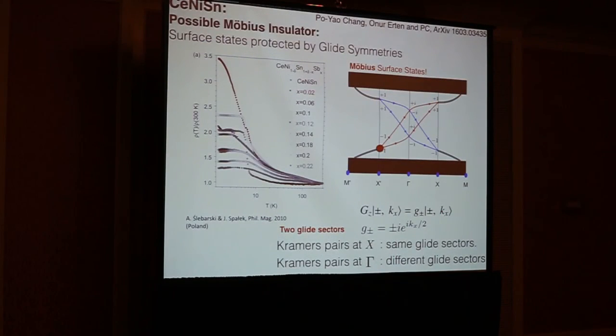And let me just mention a few other things. One of the other systems that may be topological in the heavy fermion systems is cerium nickel tin. This system is a non-symmorphic insulator. It's a semi-metal, and one of the results of this extensive analysis of topological states of matter is that non-symmorphic crystals have glide symmetries that can protect surface states. And they lead to these rather exotic surface states with a winding, which the Japanese community calls a Mobius insulator. In North America, they're called hourglass insulators.